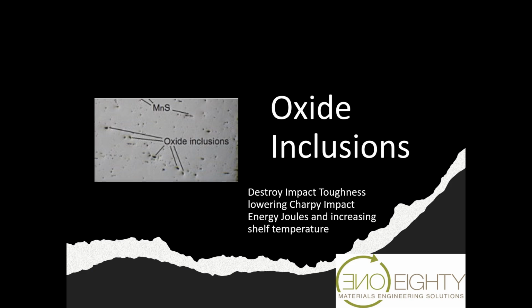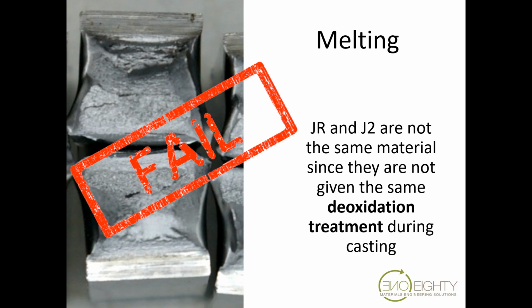So these oxide inclusions are very bad news for Charpy impact toughness, and for increasing the shelf temperature and the ductile to brittle transition temperature to higher temperatures. Okay, so JR and J2 are not the same material since they are not given the same deoxidation treatment during casting. That's a simple conclusion that we can draw there.